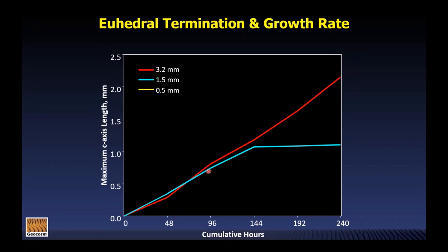So interestingly, we were growing at the same rate as a larger crystal for a while, but then all of a sudden the rate dropped off such that at the end of the experiment, our net rate was a lot slower. Interesting. All right, so now let's take a look at the growth on an even smaller crystal or smaller domain. So it also grew at the same rate in the first 48 hours. However, it then went through this transition. And once it went through this transition, the rate of growth in this regime was the same as the rate of growth within this regime on this larger crystal within measurement uncertainty. The only difference here seemed to be the fact that we went through this transition at an earlier point in growth on this smaller domain.